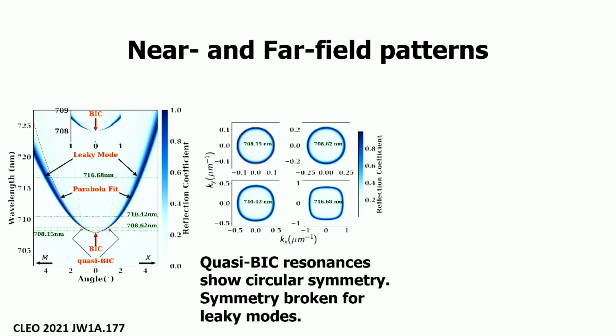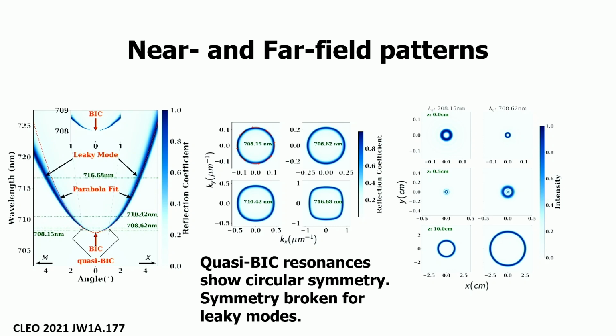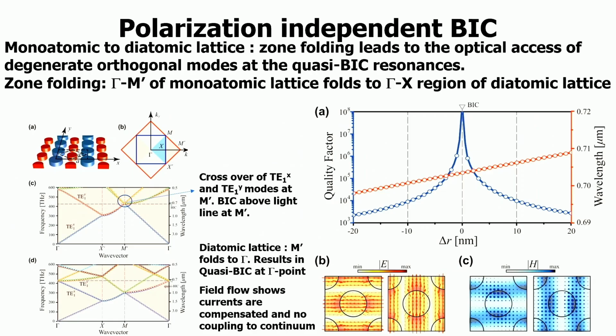For example, it has circular symmetry compared to off resonant, which reflects the square lattice symmetry of the background lattice. And the near field is more interesting because it shows these interference patterns compared to the off resonant excitations. Right. So we showed polarization independent BIC in this case.